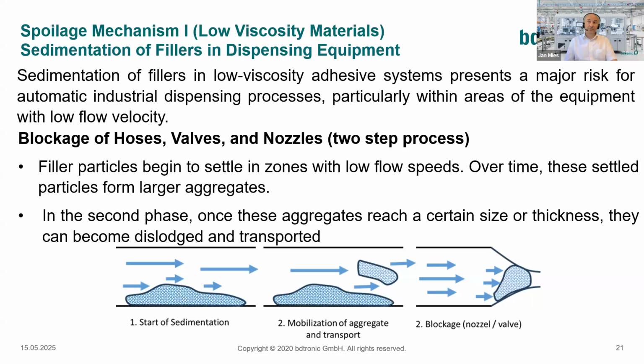On the next slide, we jump right into the first spoilage mechanism, which is typical for low viscosity materials, which I showed you on my second slide. A typical phenomenon is sedimentation. The material has a low viscosity, and it tends to sediment not only in the original container, but also in the automatic equipment. This example shows a typical phenomenon: when you have a low velocity inside a hosing or a piping system, those filler particles tend to sediment in the hosing and piping.